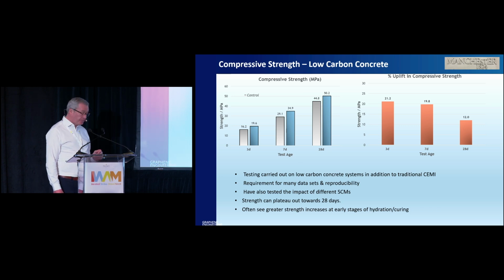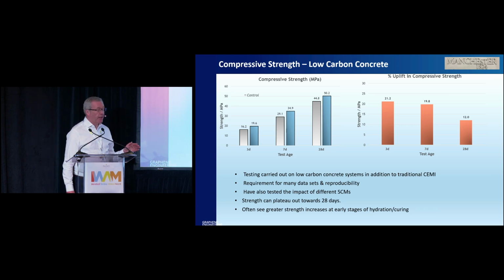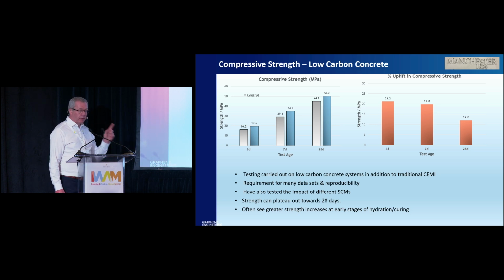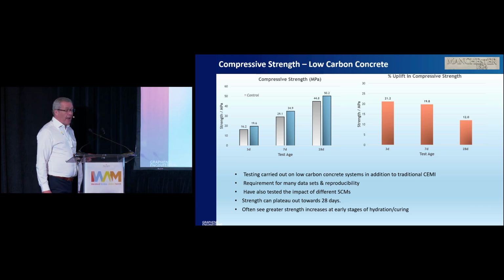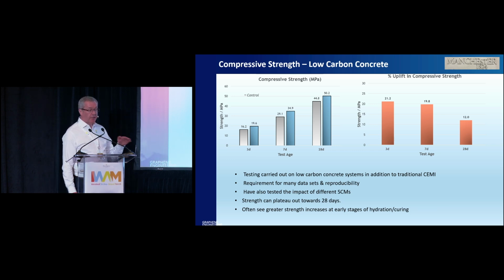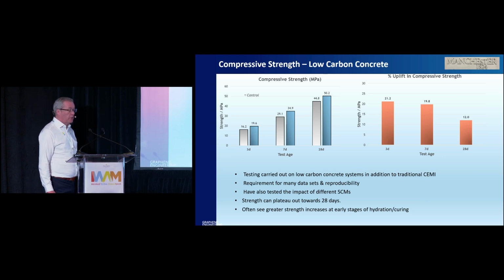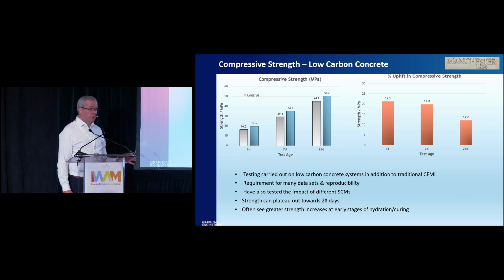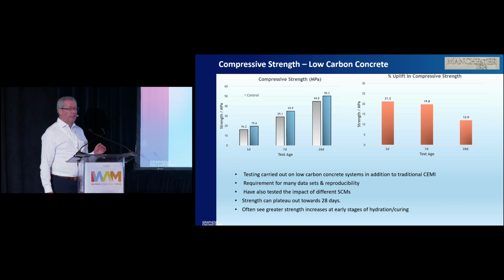So this data here is actually standardizing that data. The control is the CEM I standard, and these trials have been done with other partners as well. If you take the control and then the graphene dispersed in liquid form, we've had consistently about a 20% uplift at 3-day, 7-day and 28-day. We can get higher, but this is taking a standard baseline. We've done about 16,000 tons of concrete in different conditions, with different aggregates and different surfactants, and this is a good baseline measure now.